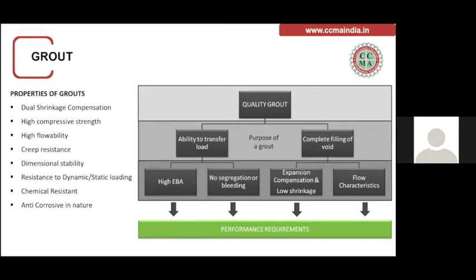So the shrinkage should be as low as possible, so that no void is created at a later stage. And the flow characteristic, because you have seen the joints, the grout has to flow from one point to another, and if the flow characteristic of the grout is not proper, possibly the grout will get blocked in between the connections. So these are some important parameters which we should definitely look into during the evaluation of grouts. And when we see all these requirements being fulfilled by the grout, then we can say that all the performance parameters are being achieved.